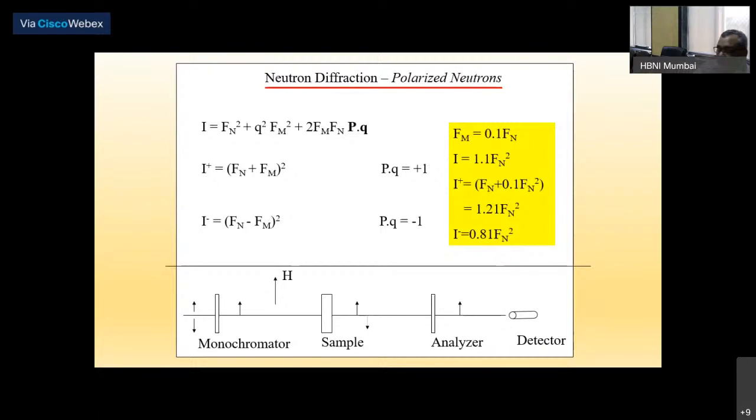I wish I could use the blackboard. See, you have a magnetic structure which is a ferromagnetic lattice. In the ferromagnetic lattice, the periodicity of the magnetic structure is exactly the same as the periodicity of the lattice structure. In that case, if I am below the Curie temperature of that magnetic material, then I will get the Bragg peak due to nuclear scattering, but it will be an increased Bragg peak because I also have the contribution from the magnetic form factor, from the magnetic structure, which is sitting right on top of the nuclear Bragg peak. So it adds to the intensity.